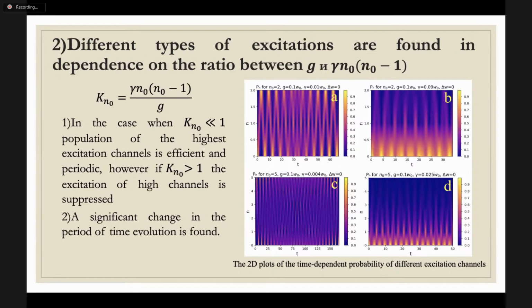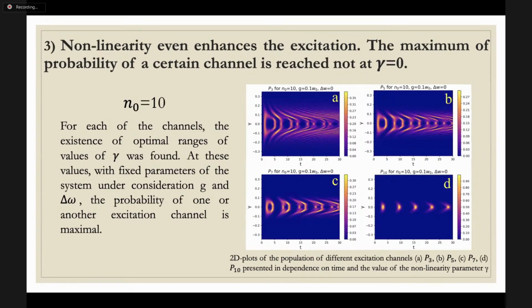So if the nonlinear interaction prevails, so when K is more than 1, the excitation of the high order channels appears to be suppressed. So we should see figures B and D. In addition, in the case of strong nonlinearity, the interaction period is significantly reduced. So it could be expected that the presence of nonlinearity would lead to large suppression of different channels, but this is not always the case.